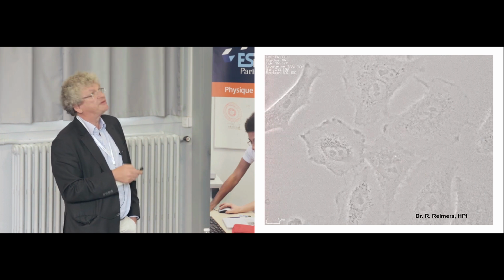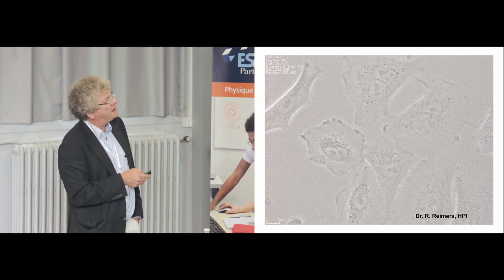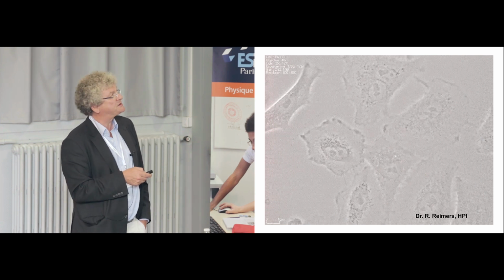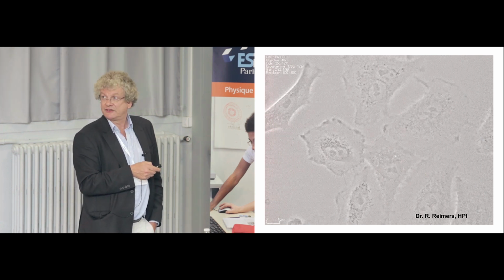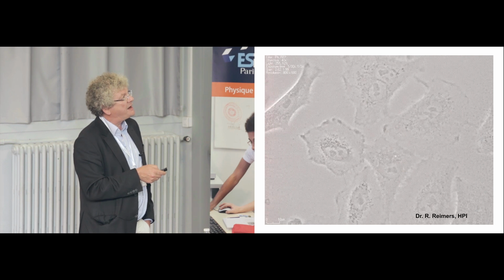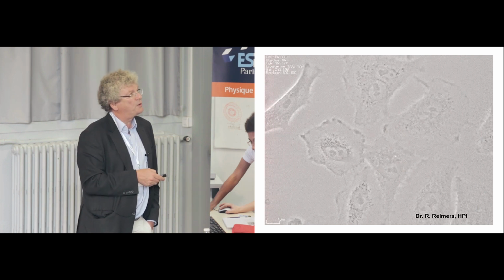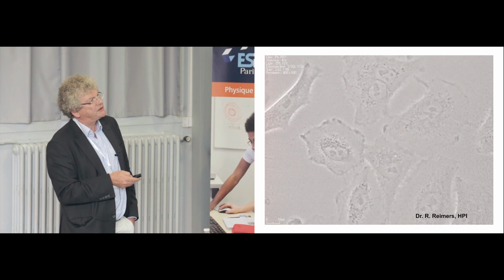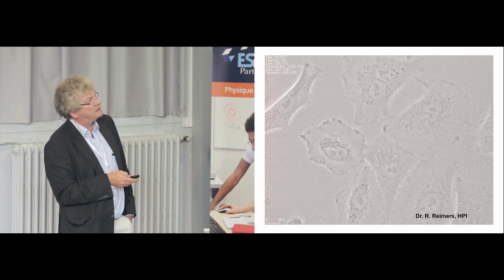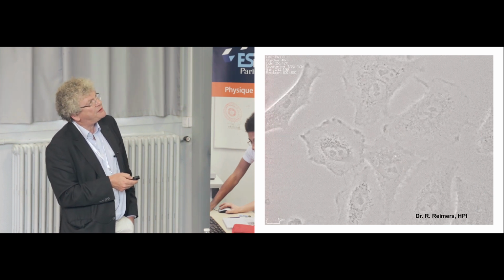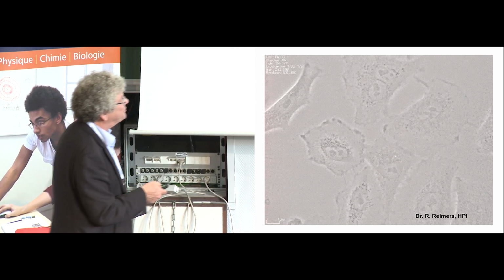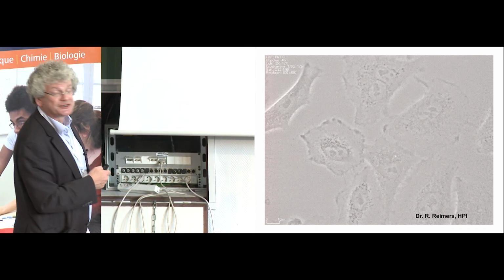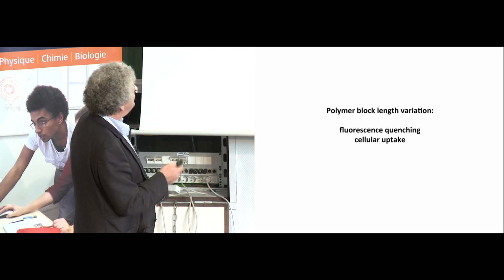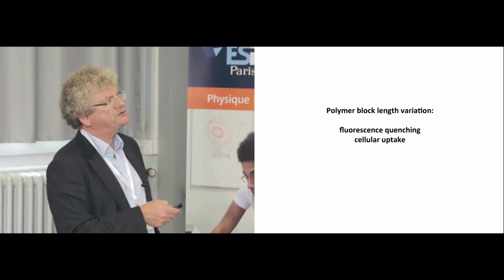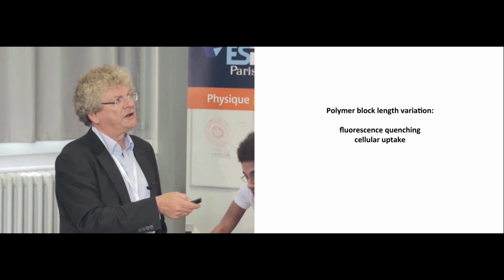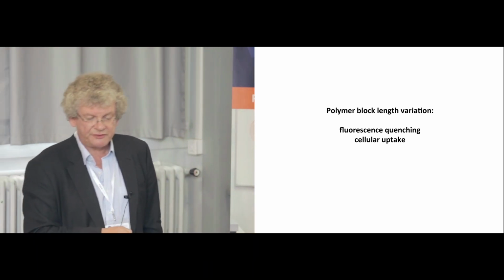And what you can see, so it's a little bit light here, there is unspecific uptake by the cells. The blue one is the cell nucleus, and the red dots here are the quantum dots. So larger ones also here, 8,000. Here, 14,000, you can't see it because of the illumination, but with 14,000, there is no uptake anymore. And it's really starting from 10,000 or so molar weight until this value. This is an optimum value for the size.